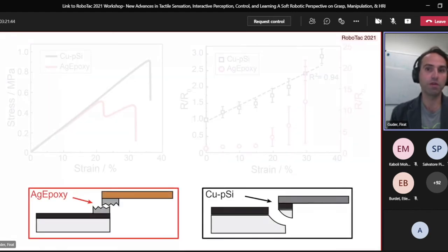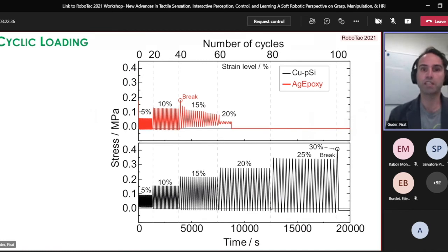When we investigated the material junction microscopically, we see that the contact between the copper silicone composite contact and the underlying silicone elastomer is so strong that actually the elastomer itself fails first before the contact. And we really like this because it shows that the material itself will catastrophically fail when it goes beyond the limits of operation, and not just fail a little bit and give a wrong result. So catastrophic failure in this case is a good thing, especially if you want to use it for biomedical applications and so on. Actually for any sensing application, it's not a good idea to have erroneous results.